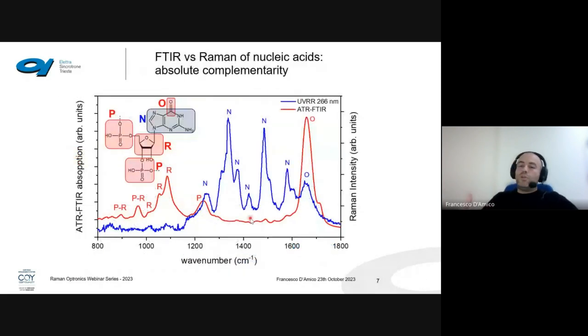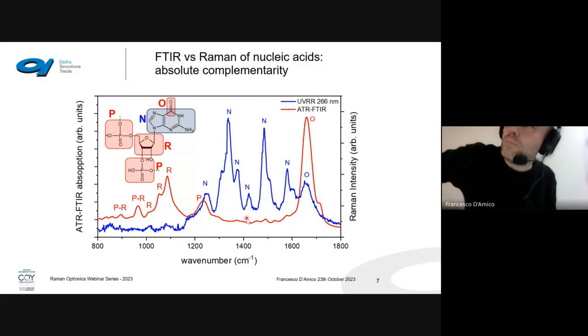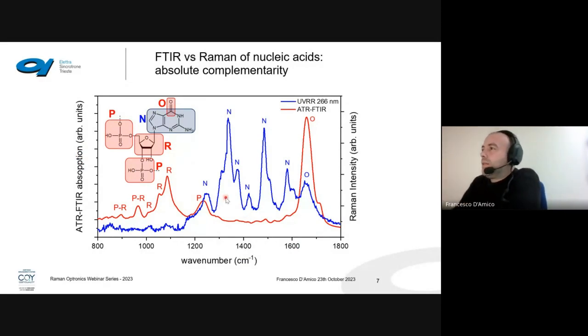What we can see immediately, just to provide you a real example of what I've explained up to now, is the spectrum of DNA. The red one is the FTIR spectrum, the infrared one. The blue one instead is the ultraviolet resonant Raman. Raman spectra and infrared spectra are completely different, although they belong to the same sample. This part of the molecule, which has a high dipole moment, can be detected very well with infrared. Otherwise, the aromatic compounds coming from the nitrogenous bases have a higher polarizability, and therefore their normal modes are better enhanced with Raman spectroscopy.